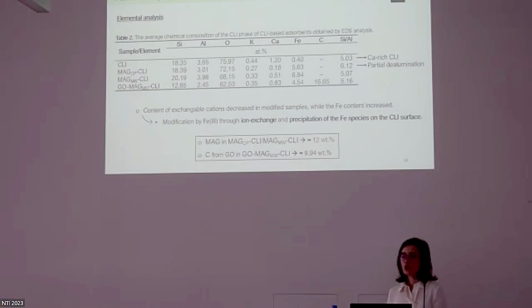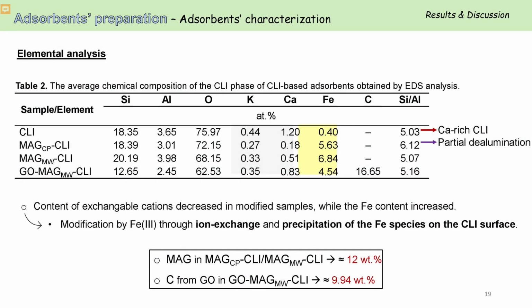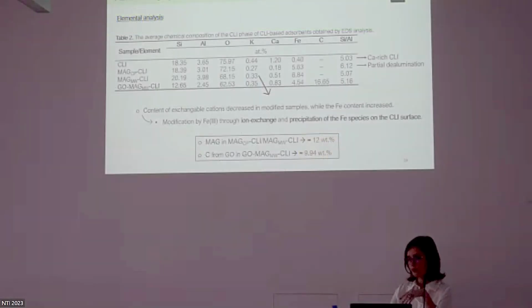So the average chemical composition obtained by EDS showed that the silicon to aluminum molar ratio of clinoptilolite changed by modifications. This indicates the partial dealumination of the clinoptilolite structure during the modifications. Further, the content of exchangeable cations in modified samples decreases, while the content of iron increases. And since the iron increase is much higher than the decrease of exchangeable cations, the modification with iron oxide particles possibly occurs through not only iron exchange, but also precipitation of iron species on the clinoptilolite surface.